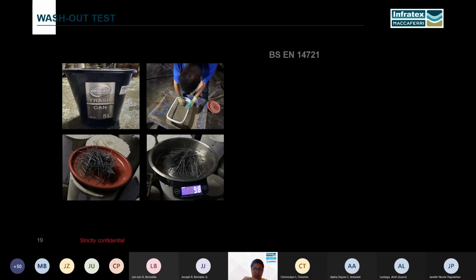For this specific washout test, the fiber dosage is 20 kilograms per cubic meter. So for a 5-liter bucket, the theoretical amount of fiber is 100 grams. After doing the washout test, we recorded a result of 98 grams, telling that the fibers are well mixed within the concrete.